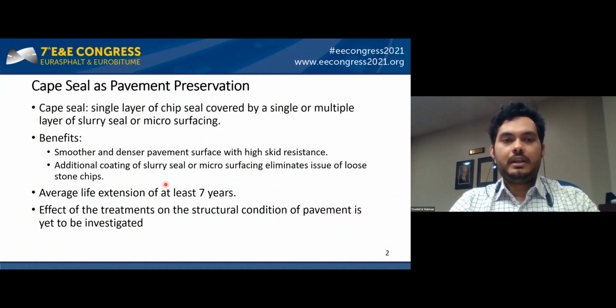Before we go over the details, I would like to go over a little bit of background of the cape seal and pavement preservation. So the cape seal is a single layer of chip seal covered by a single or multiple layers of slurry seal or microsurfacing. Some of the functional benefits that are quantified are a smoother and denser pavement surface with high skid resistance, and the additional coating of slurry seal or microsurfacing eliminates the issues of loose stone chips.